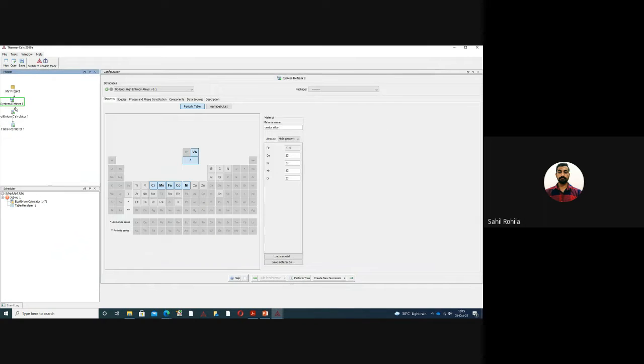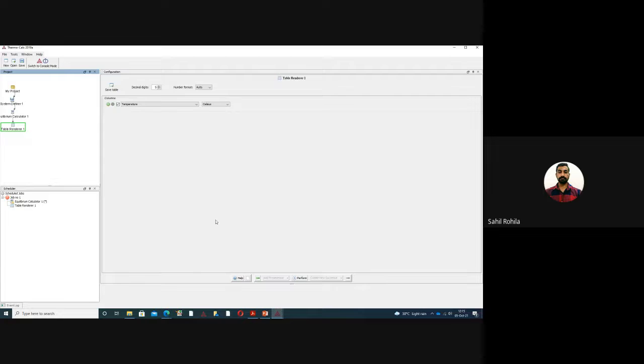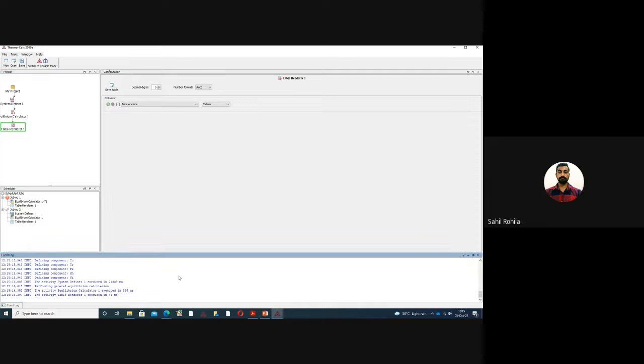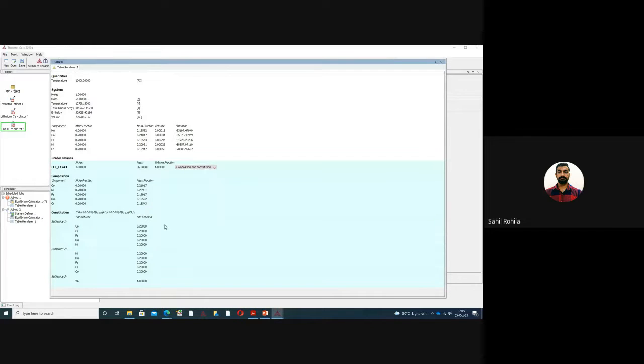Now cobalt, chromium, iron, manganese, nickel, that is the Cantor alloy, is an FCC phase alloy. If I add aluminium to it, for example, and I uncheck manganese, aluminum 20. So now earlier the phase was FCC. Now we can see. Just wait.